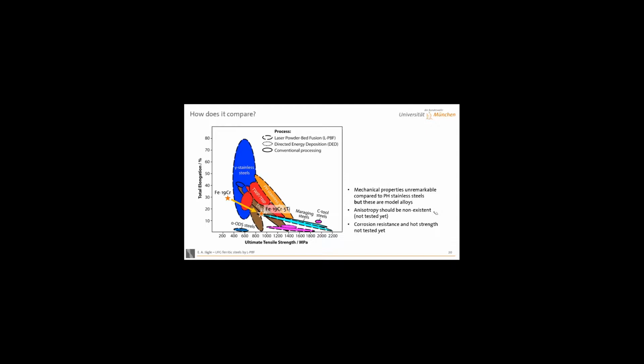Okay. So we're still not going to win a lot of awards with this model alloy. I mean, if we plot this together with lots of different other steels and stainless steels, then you see that we go from abysmal to unremarkable in mechanical properties. So if you are in industry and you want a material, just go ahead and buy PH steels, I would say. But from the academic point of view, it was a very nice study, I think. For us, at least, it was fun. And in the end, it was a binary respective ternary model alloy.